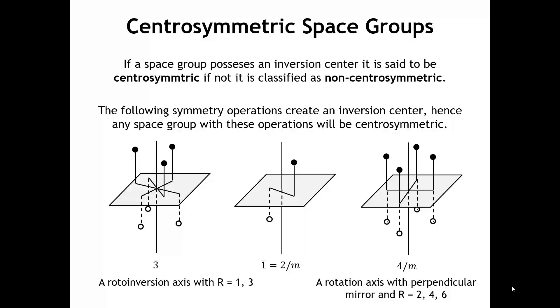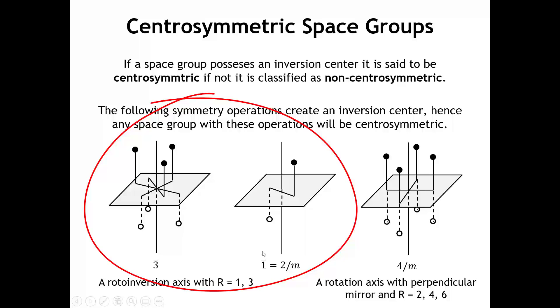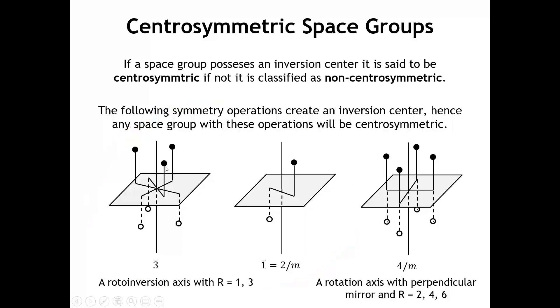How can we look at a space group and know whether it's centrosymmetric or non-centrosymmetric? It depends on the point symmetry of the crystal — the Bravais lattice is irrelevant. We create an inversion center when we have an explicit inversion center, so a space group like P1-bar would obviously be centrosymmetric. There are also other operations that inherently generate inversion centers: rotoinversion axes where the axis is an odd number — either 1-bar or 3-bar.